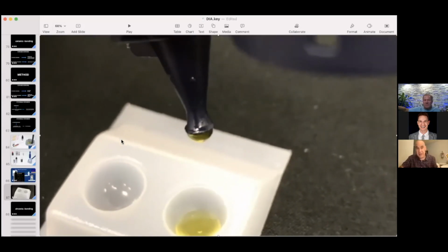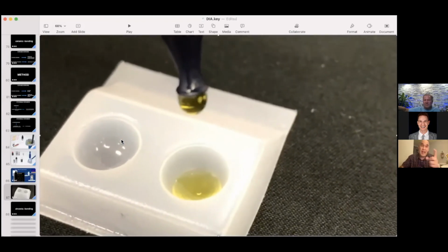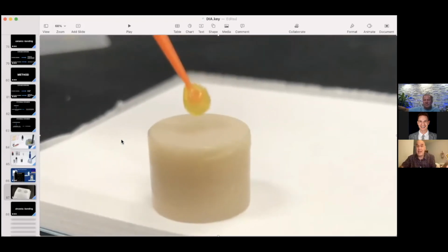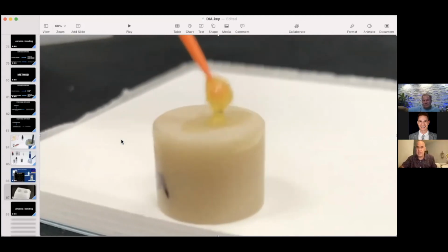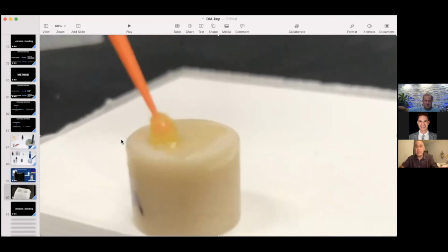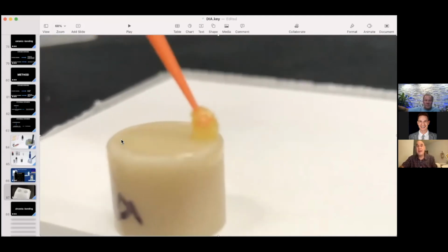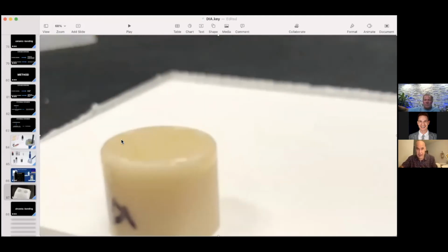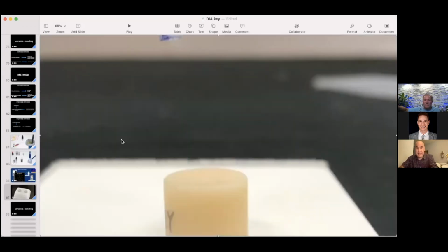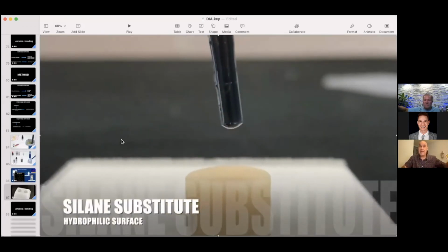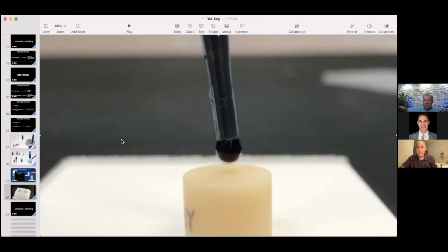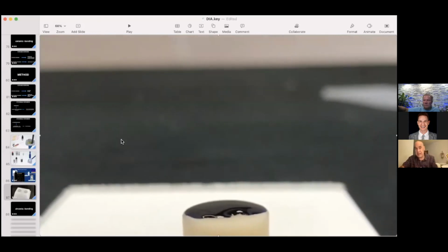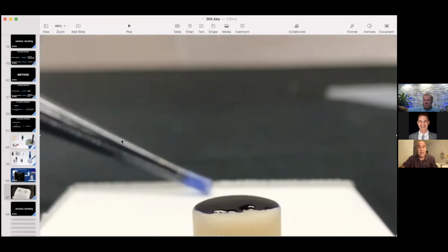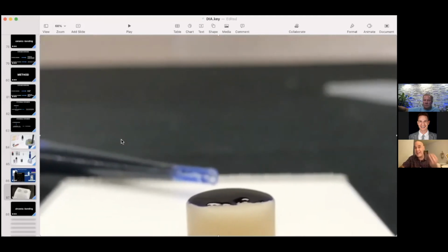I have nothing against 3M, but they do sell an adhesive that contains silane, and they tell you this is going to substitute your silane. So I'm applying Scotch Bond Universal to my etched lithium disilicate ingot, okay? If this silane substitutes my regular silane, then I should have a hydrophobic surface. However, what I'm seeing is a hydrophilic surface, meaning that the silane in that adhesive did not react with the surface. Okay, this is a visual.